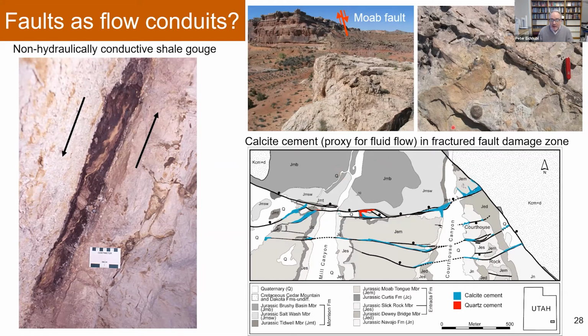And here an example of the Moab fault where we mapped the distribution of alteration of diagenesis, in this case, calcite precipitation, that is confined to locations where opening mode fractures form, and they form at specific locations along the fault, such as branch points or steps in the fault, or where the fault changes direction. Okay, so that's tied to the formation of opening mode fractures along the fault zone. So ultimately, it is the opening mode fractures that control the permeability of the fault zone.